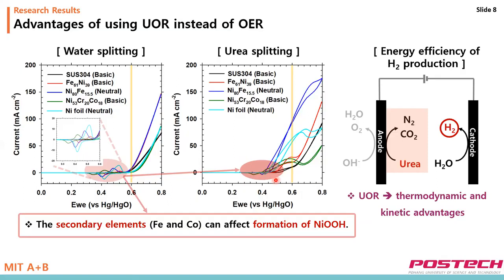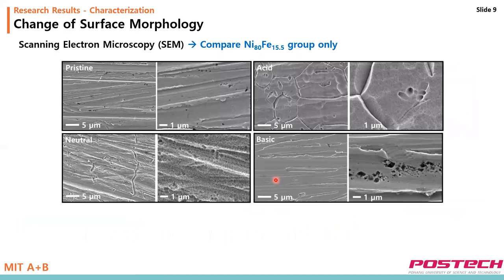In more detail, when urea is in solution, current increases from near the voltage of nickel oxyhydroxide formation. This result means that nickel oxyhydroxide is the main catalyst for UOR, so formation of nickel oxyhydroxide is also important. So it is important to find out why UOR activity has increased.